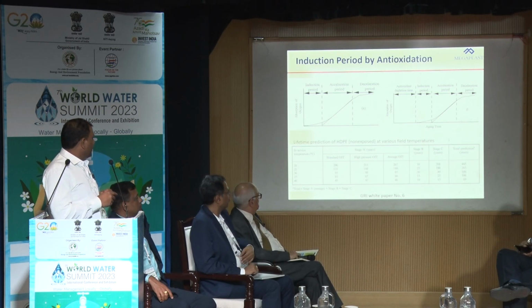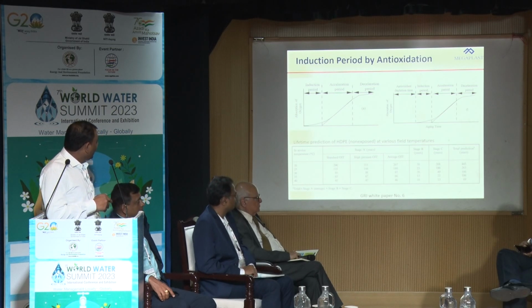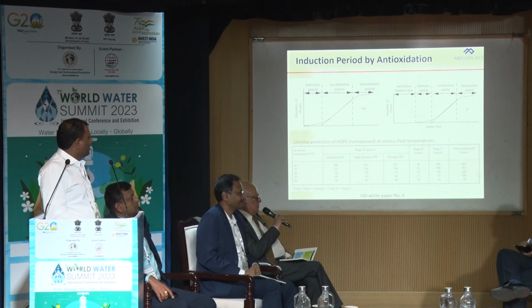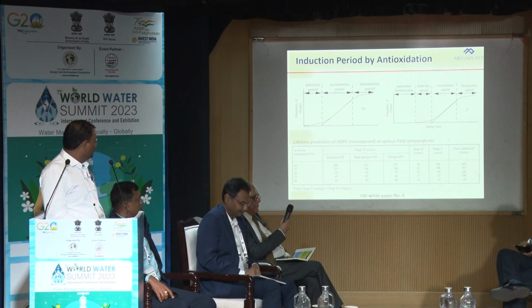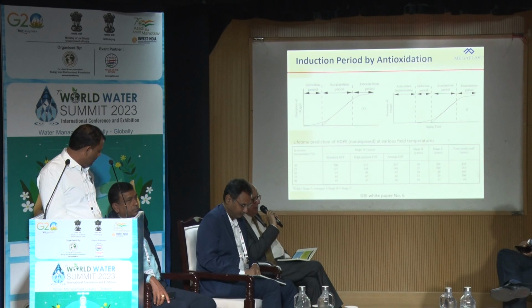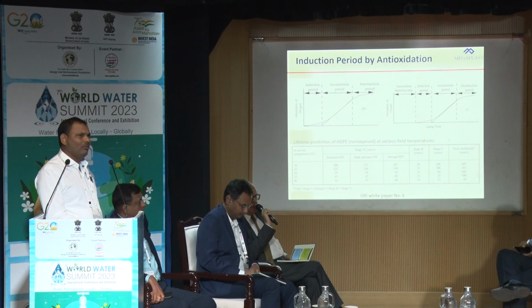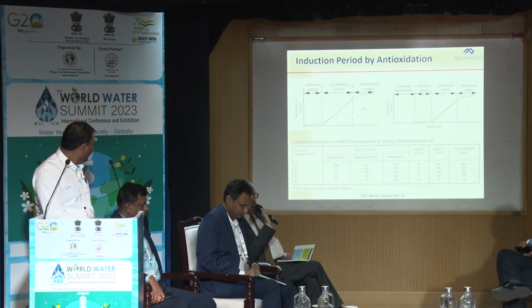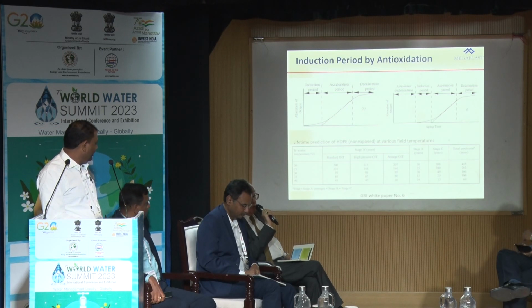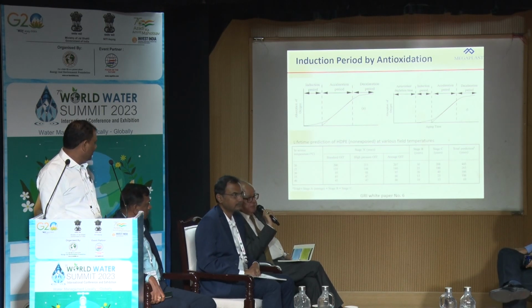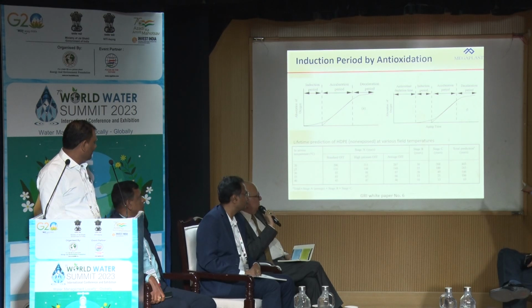Why not more than 40? Sorry? Why not more than 40 degree temperature? It can be done, 45. You see, sir, you are marketing these products in tropical countries also. And now with global warming coming, the ambient temperatures are rising, and particularly in regions where there's stony subsoil, the temperatures can even hit 50. That's true, sir. So if you want them to be used at 50, then your testing should go up to about 55 or 60, extreme conditions, because it is decreasing very drastically.